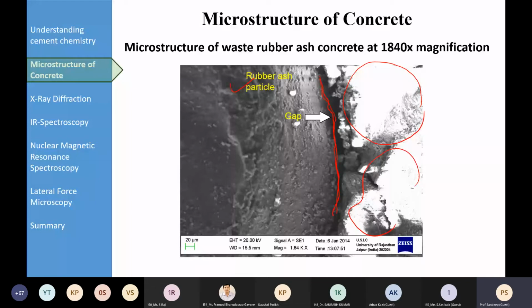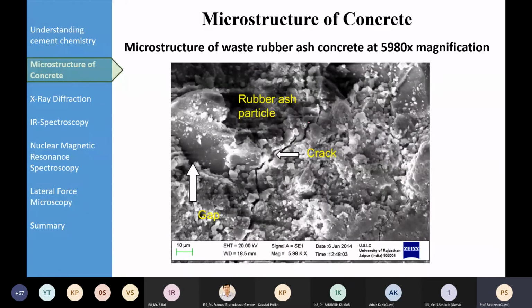Like here you can see at a greater magnification level, you can even see the cracks in the rubber ash particle themselves, and you can see this gap, or rather interfacial transition zone. Now the rubber ash particle, which otherwise is difficult to even see by naked eye, you can see even up to a crack in that, and you are able to see the gap there also, which is a sort of interfacial transition zone. We will not go into much detail, but this crack in the rubber ash particle will also have its own effect on the cement matrix, or on the behavior of the concrete.